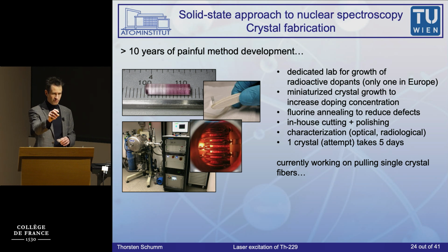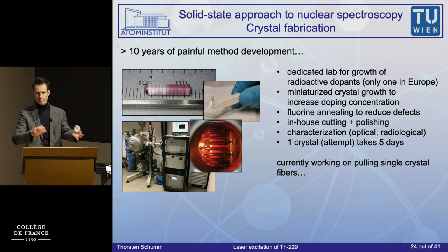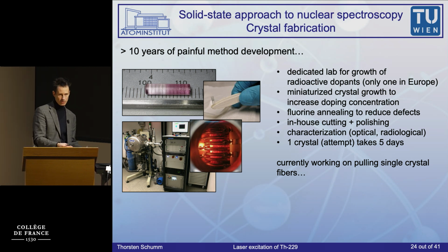And then we put thorium fluoride in there, and then we melt the whole thing, but not the full volume, only 2/3, and then we let it solidify again, and then we have the crystal structure, but we have thorium fluoride doped into this material. These are very small crystals because we have very little of this material. We have microgram quantities, and we don't want to dilute this over a large volume because ultimately the laser will only go through a few cubic millimeters or less, so it doesn't really help us if we have a large crystal. Then the thorium will be sitting in corners where it produces background but no signal.